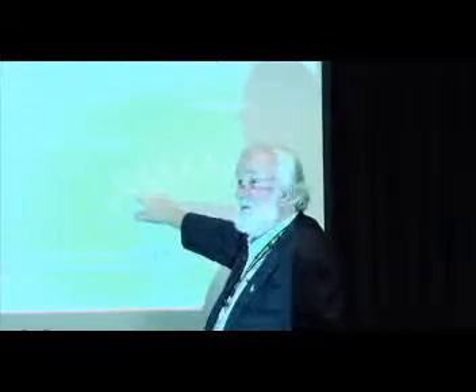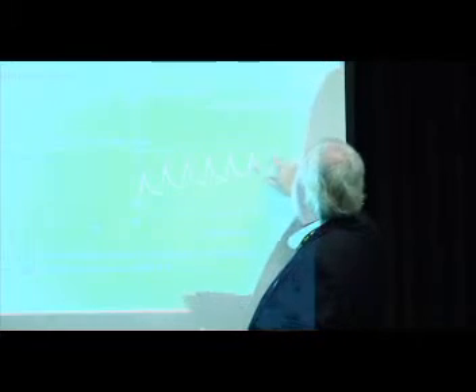And so what happens is the concentration of carbon in the austenite stays here, and you've spent all this time making carbides, and the flux isn't coming through. So the scheme that people use is a whole series of pulses, and you can see how that works. You boost, pulse and diffuse, pulse and diffuse, pulse and diffuse, and then it works much better. If you ever wonder why there are a lot of short pulses for some of these systems, that's what they're trying to get around.